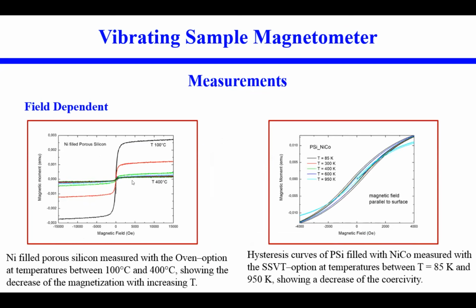In the left diagram, you see hysteresis curves of nickel-filled porous silicon measured with the oven option between temperatures of 100 and 400 degrees Celsius. And it shows the decrease of the magnetization with increasing temperatures. And the Curie temperature in this case is around 360 degrees Celsius. So it can be used to figure out the Curie temperature of samples.